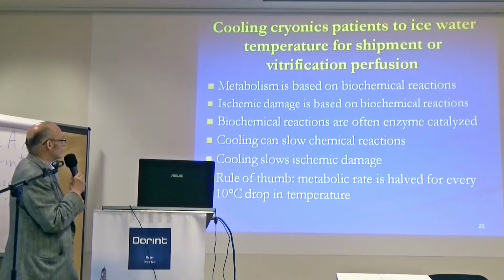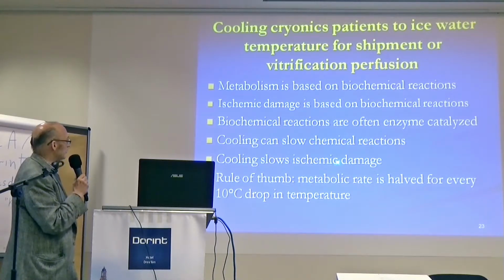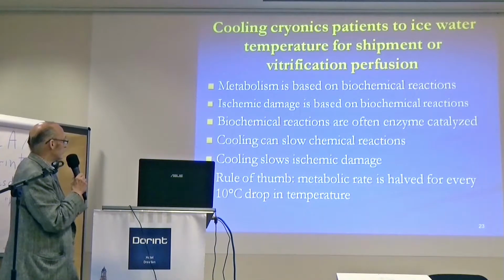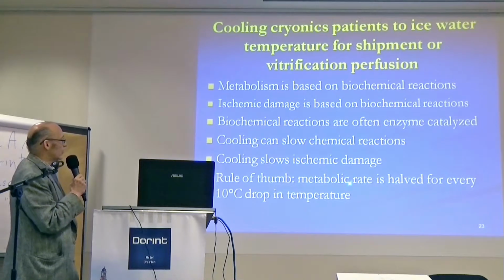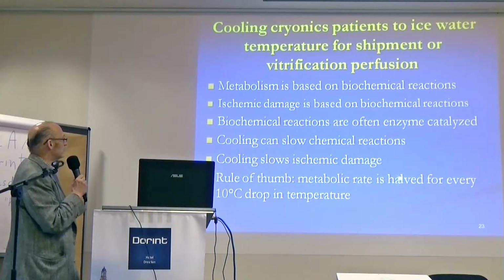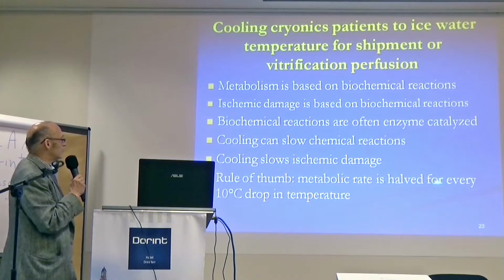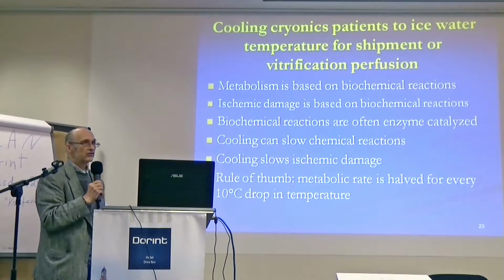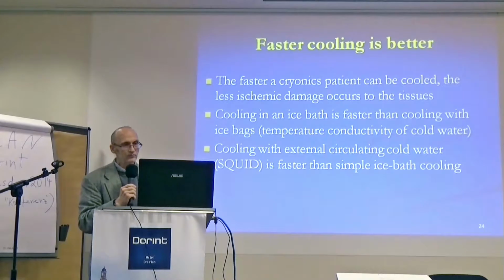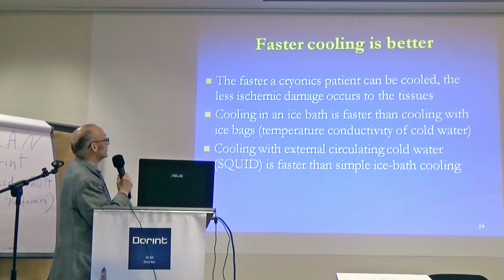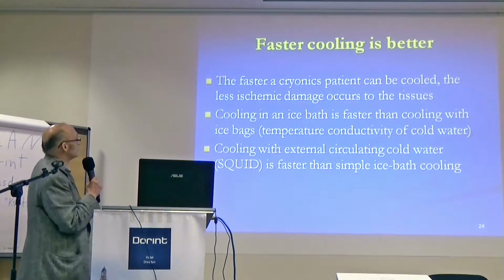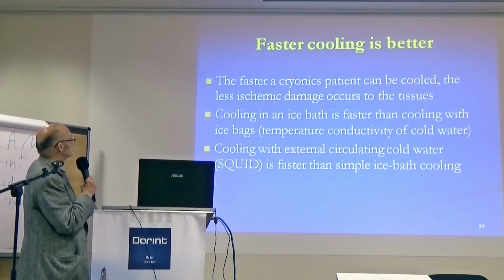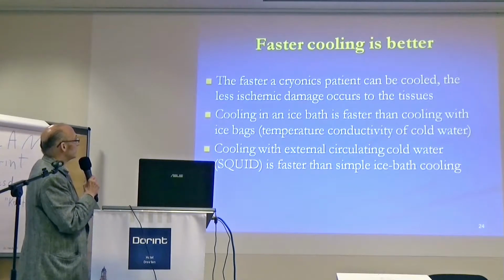Cooling can slow the ischemic damage. It can slow chemical reactions, and that means slowing ischemic damage. The rule of thumb is that metabolic rate or chemical reactions are halved for every 10 degrees Celsius drop in temperature. So faster cooling is better. The faster a cryonics patient can be cooled, the less ischemic damage. And cooling in an ice bath is faster than cooling with ice bags.